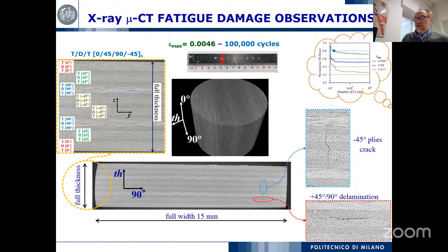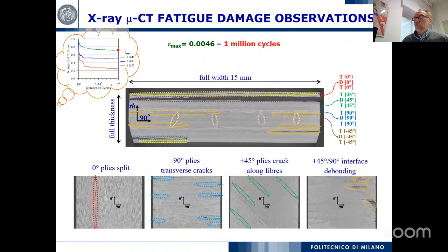Increasing the number of cycles, this fragmentation will multiply, so you have multiple fragmentations mainly in the same ply, and this fragmentation is converted to delamination that finally leads to complete splitting of the material. This is after 1 million cycles. But after 1 million cycles, even though you have such a huge delamination here or in another position, the high elongation ply still continues to carry the load, and so your material does not fail completely.